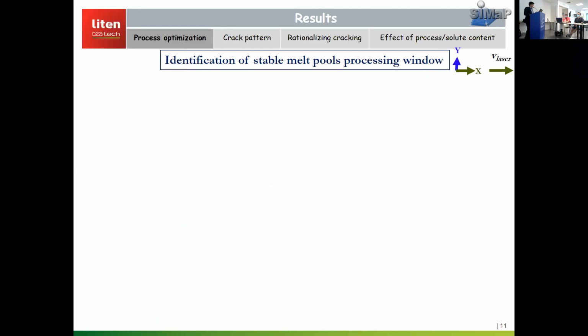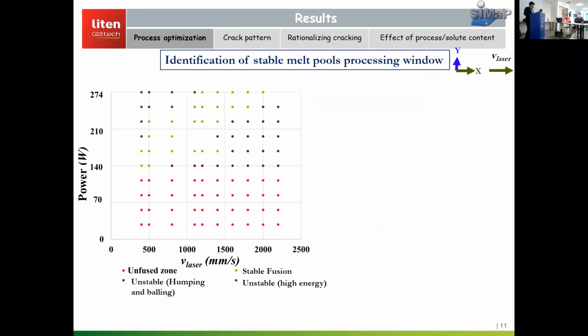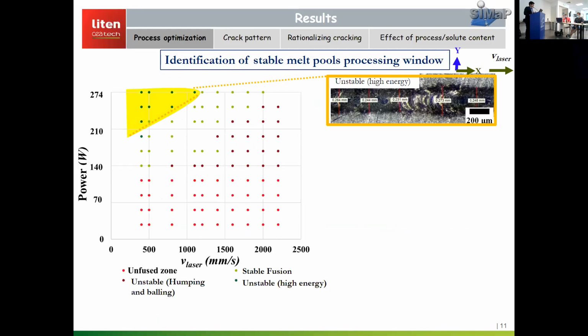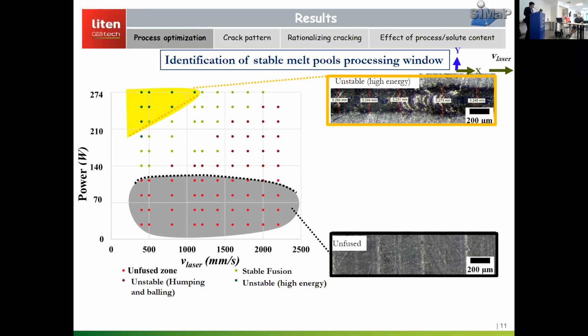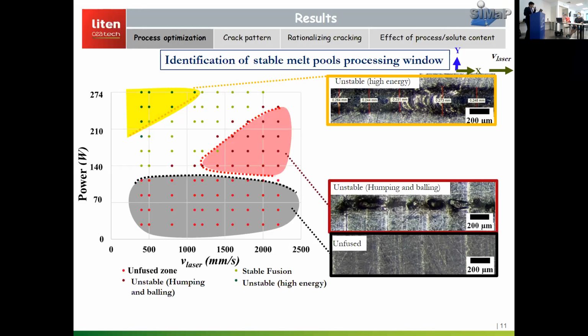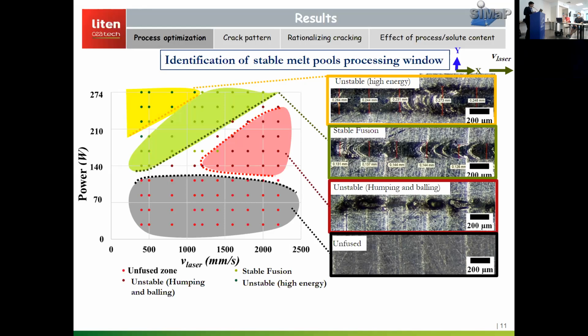If we look at the similar different conditions in terms of the processing map, for example, the y-axis is laser power and the x-axis is laser speed. If you have sufficiently high energy, you can end up getting unstable melting conditions. This can be due to the intense convection flow due to the high laser energy density. If you are at low energy density, for example, low powers, you can get into an unfused region. If you are at sufficiently high laser speeds, you can get humping and balling as explained in the previous slide. And there can be particular stable melting conditions, as we have identified in the green zone here. So this was identified in the 1D track analysis.